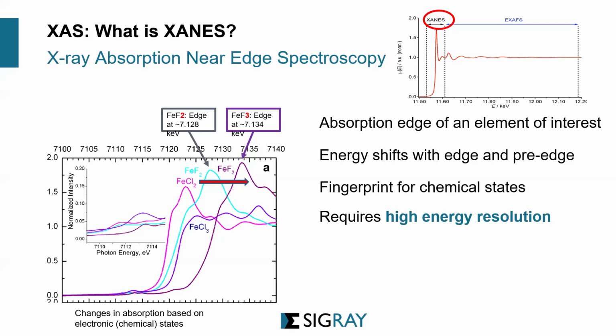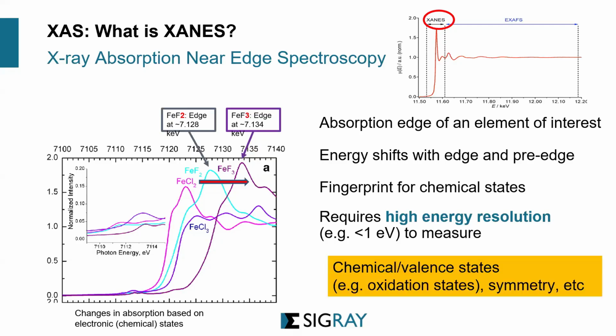Also, because you are looking at the edge and pre-edge, this is the edge and this is the pre-edge, the little bumps before the sharp absorption edge are called the pre-edge. They require your tool to have pretty good energy resolution in order to capture all these little shoulders within the spectrum. So whatever instrument you have needs to have high resolution for XANES, ideally 1 eV or less. In short, XANES allows you to look at valence states like oxidation states.